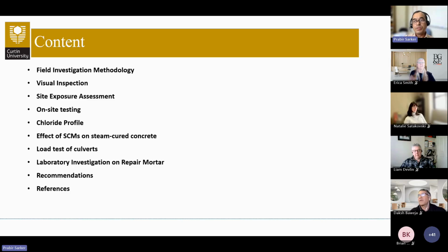So that includes some site visits - 3 site visits, a level 1 site visit, and then some more detailed visits, including a visit to do some on-site testing of the culverts on corrosion activity and electrical resistivity, and also the core samples that we collected from the sites and tested in the lab to determine the chloride profile and relate it to the observed corrosion activity.